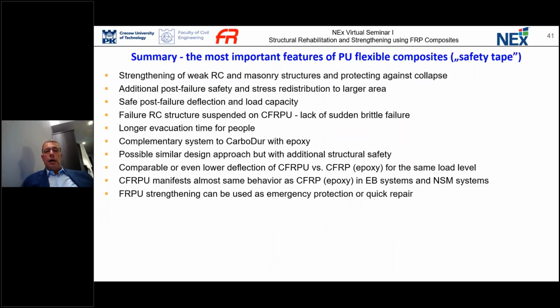To summarize my presentation, I would like to point out two groups of features. Mainly, I would like to point out that strengthening of weak reinforced concrete and masonry structures can protect the structures against collapse effectively. Using this flexible composite system, we introduce additional post-failure safety and stress redistribution, because we use a larger area of bonding material. Also, we have post-failure deflection that is visible, and it warns the user of the structure, but having a large deflection, we are also able to carry high loads.